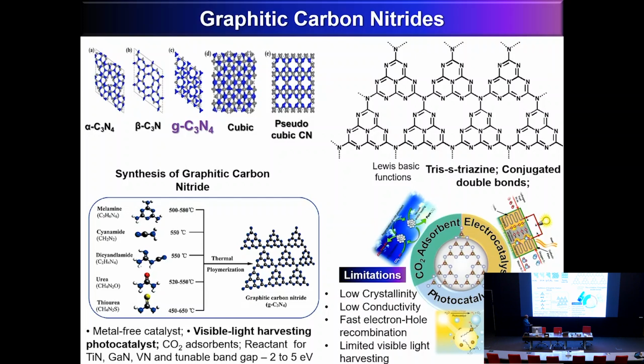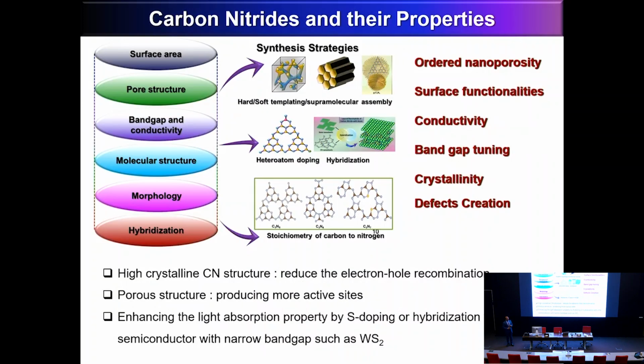But unfortunately, the performance of these materials in photocatalysis is very low because of the fast electron-hole recombination and limited visible light harvesting because of the poor band gap, that is 2.7. And what we have been doing in our center is to change that scenario. So we adopted a different strategy.